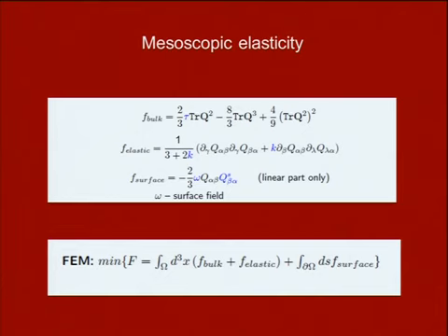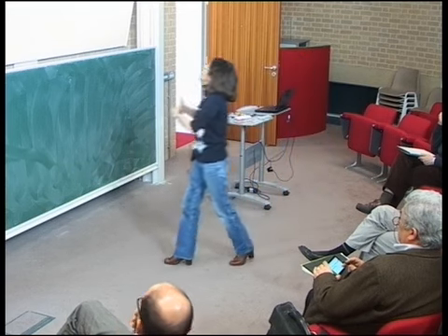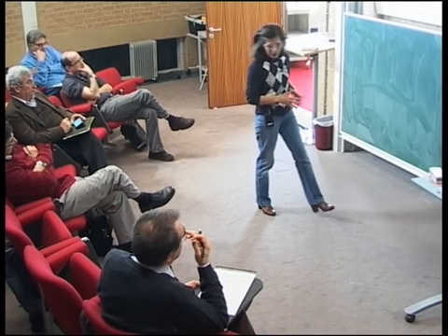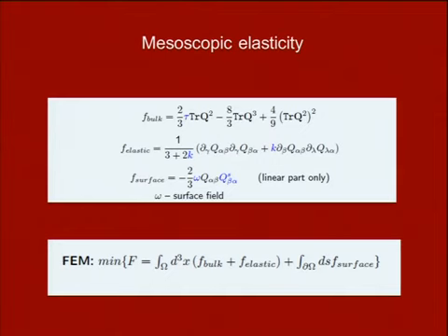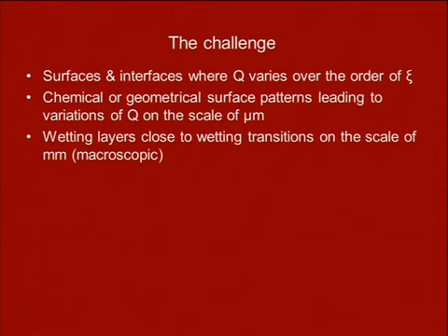But if you think about it, you don't actually have two free parameters, you only have one free parameter, because if that tensor gives you homeotropic anchoring, and if the surface, this surface that is the boundary, is not biaxial by itself, then this preferred anchoring should be uniaxial, so really the S that comes from there can be absorbed in W, and you actually only have one free coupling strength. If you have two terms, then it's slightly different. You have two surface fields like you had in the magnetic problem. And so, depending on the type of coupling, you have different coupling terms and fields.